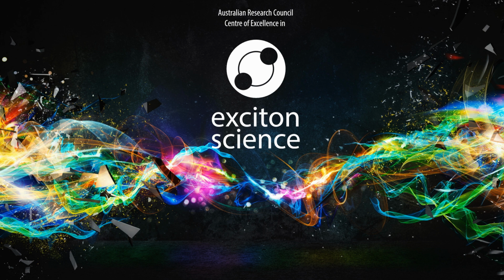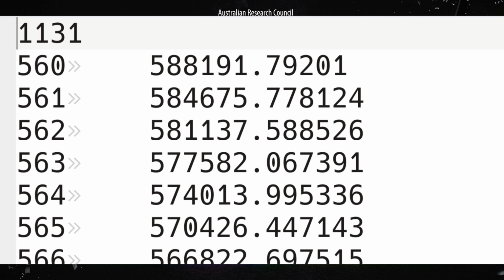The first one will be the sensitizer absorption spectrum, absorption.txt. This is the sort of data that you would measure using a UV-Vis. When you measure your absorption data, there are some important considerations. You need to make sure that the baseline is properly subtracted. You should make sure that the values of the absorption spectrum are not negative, that the maximum values are not saturated in your detector, and that the units of your absorption spectrum are per molar per centimeter, or in other words, liters per mole per centimeter.